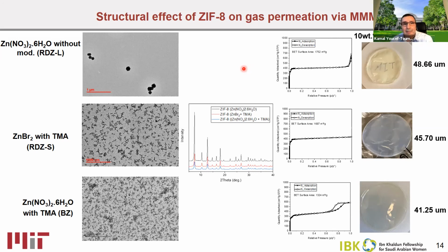Yeah. Actually, in my case, I usually get this type of isotherm, I mean type 1 and 4, when I go from the single crystal or rhombic dodecahedral to branched material. So most of the branched material show this behavior, which indicates that most of the branched material, or actually all of them, possess both morphologies, both pores, micro and meso.